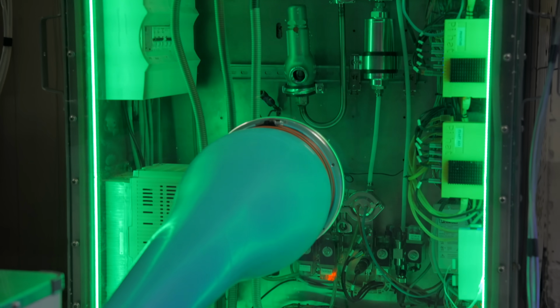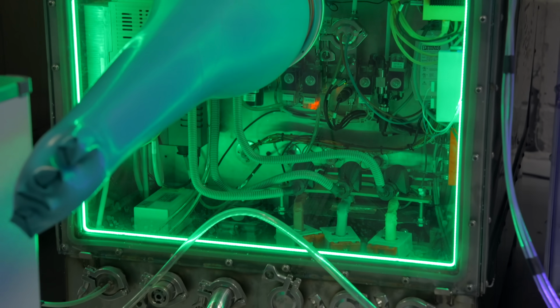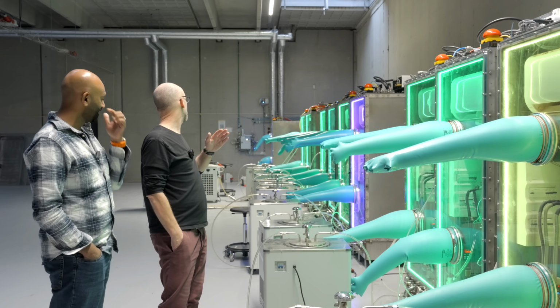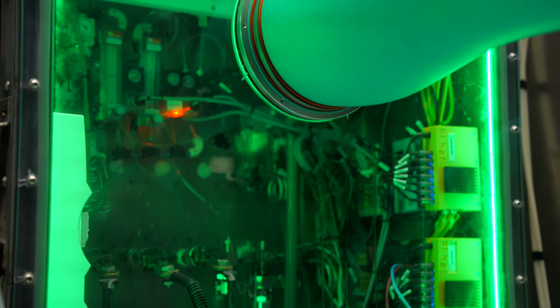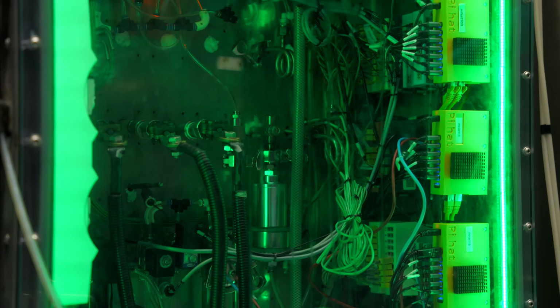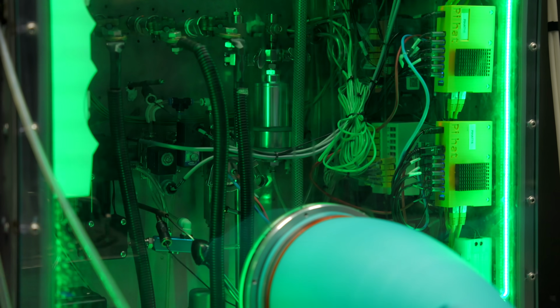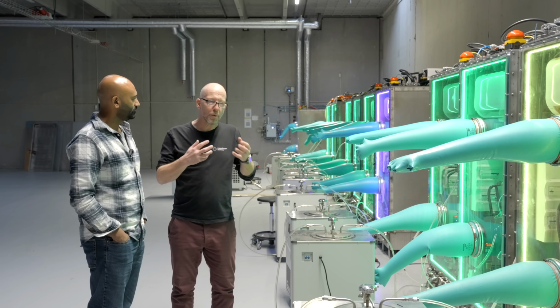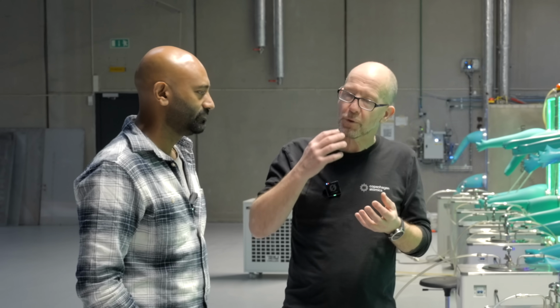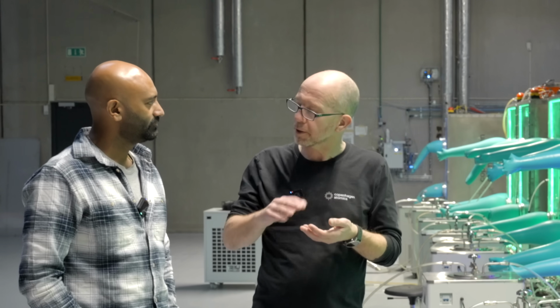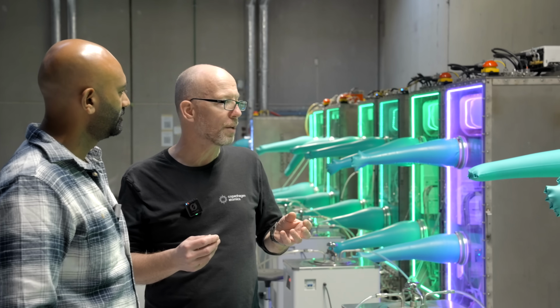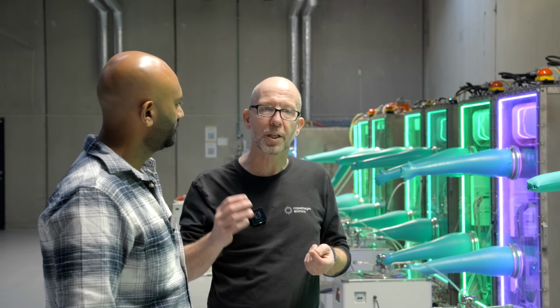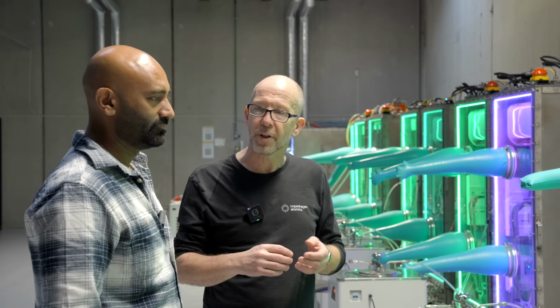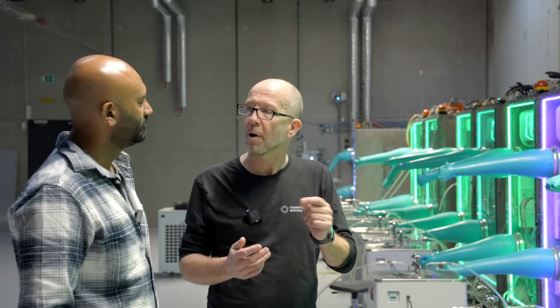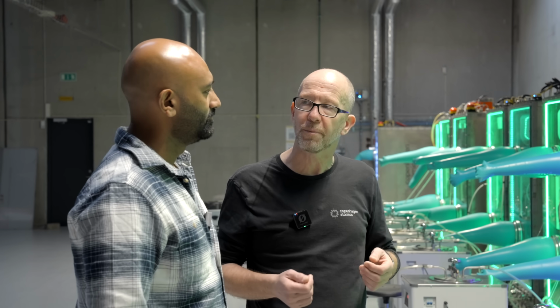600 degrees sounds very challenging. How do you withstand that kind of temperature safely for... You mentioned some of these have been running for a year nonstop. Yeah, they're running for several years nonstop. Everything here is made from stainless steel 316L, and 316L is absolutely adequate for these temperatures. And people always wonder about corrosion from molten salts. But if you have a purified molten salt, it's absolutely non-corrosive. It's the impurities that make it corrosive. So rather than use expensive alloys, we have chosen to develop engineering controls where we keep the salt clean at all times. And then the corrosion is vanishingly low, a few microns per year. So corrosion is not really something we bother about anymore.